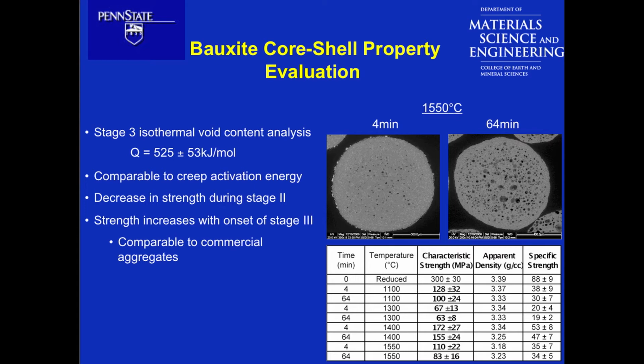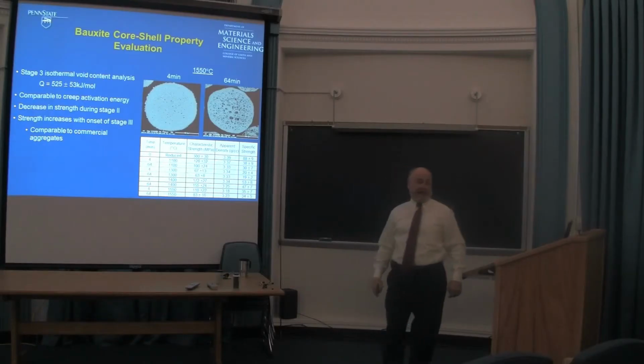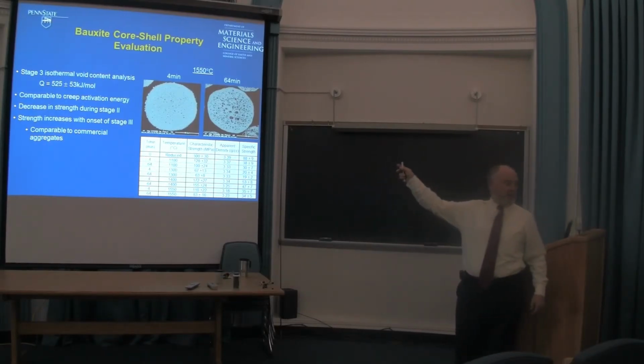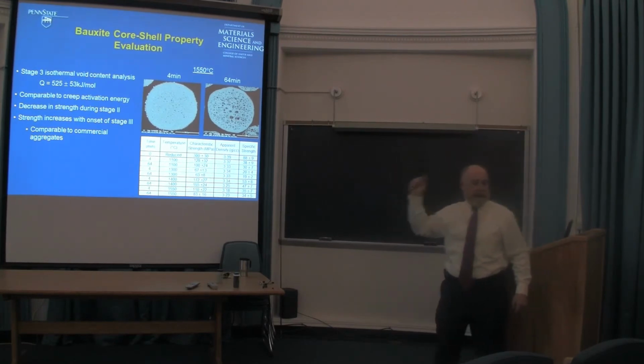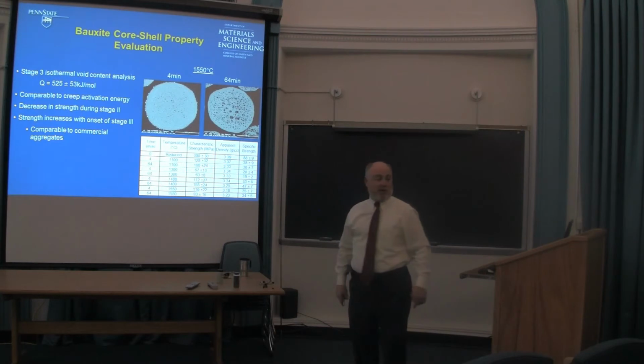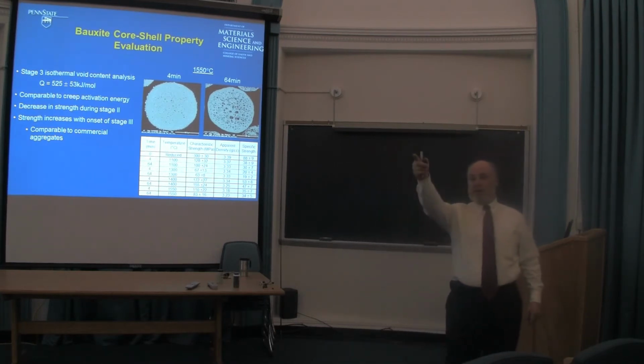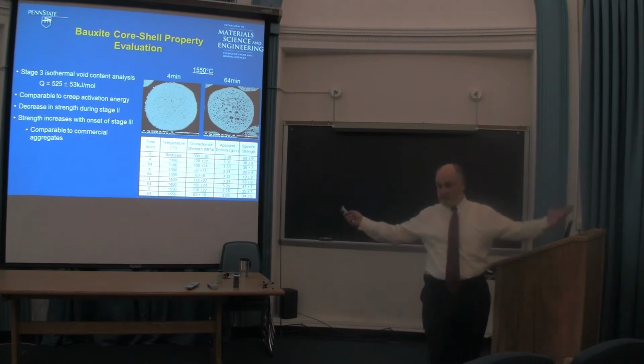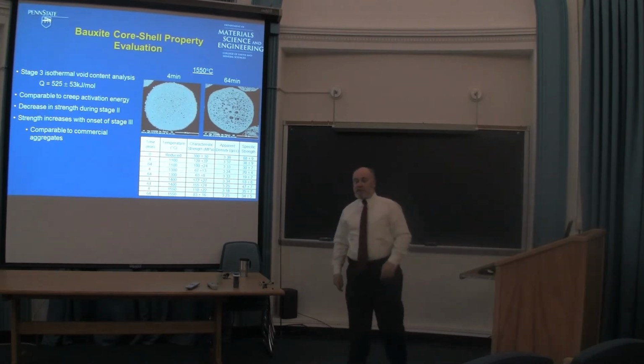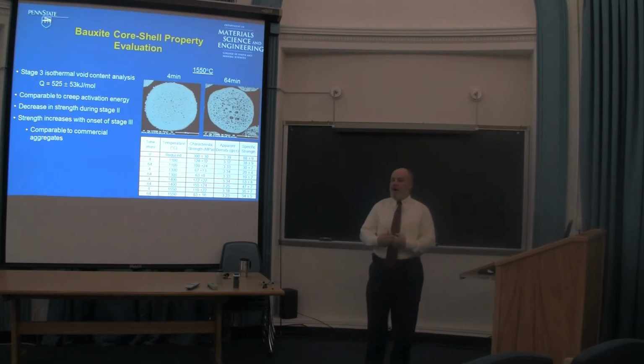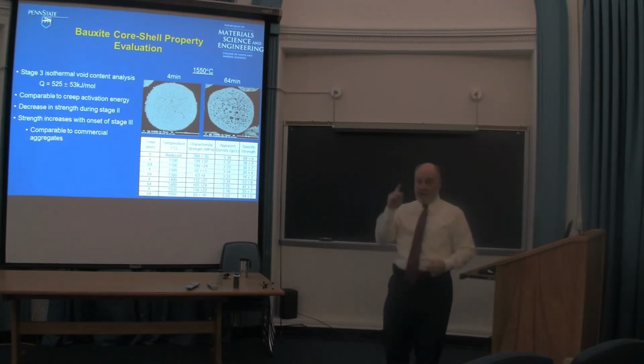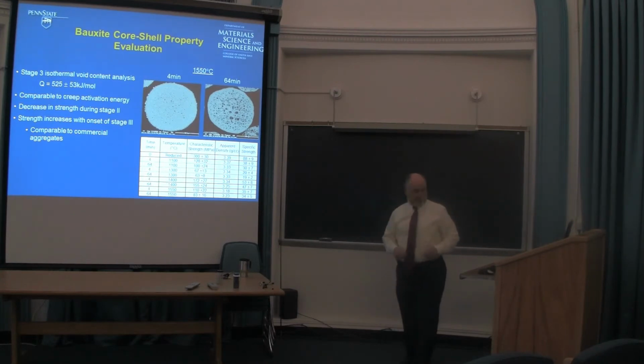After 4 minutes and 64 minutes at 1550 degrees C, by changing our oxygen partial pressure, we created gas bubbles that formed this Swiss cheese malted milk ball effect with a dense outer rind. And when you look at the activation energies associated with the evolution of that microstructure, they are almost exactly coincident with the activation energy for creep of aluminosilicate brick, done by Dick Brott in the 70s. Okay? So we know why these are forming. We know how fast they're going to form, and we can tailor our process and chemistry to be able to manipulate that. Okay?